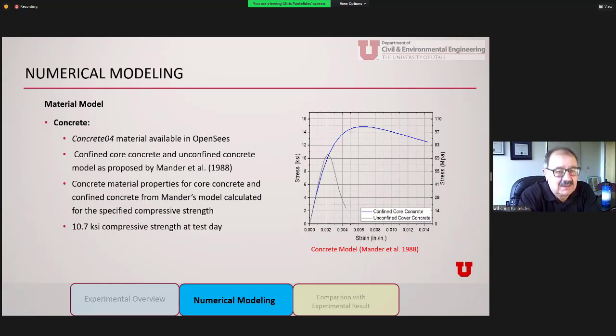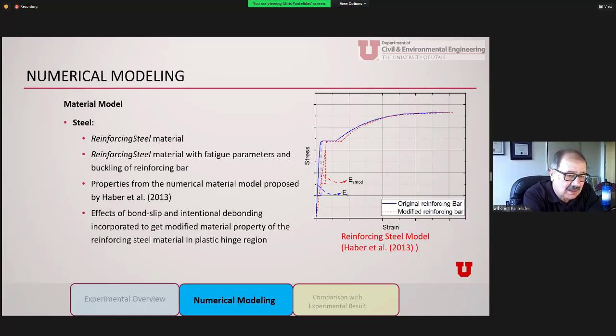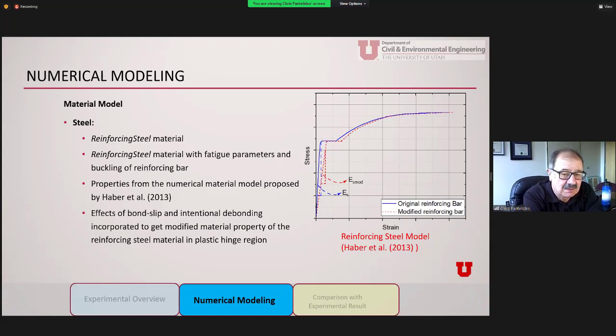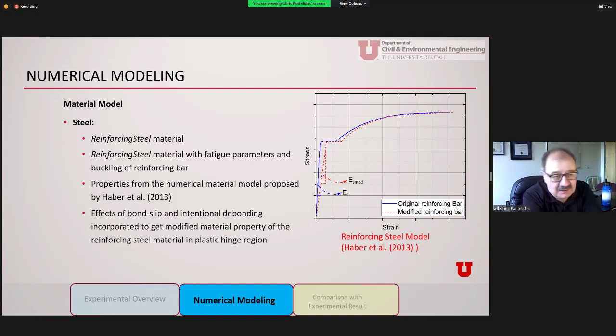The concrete compressive strength was rather high — 10.7 KSI — partly because we got donated concrete and partly because delaying testing increases strength. The real innovation in this model is how to model the reinforcing steel bars, a difficult exercise because we have two effects: in cast-in-place concrete columns the rebar eventually slips, giving a bond slip effect; and additionally in these two tests we intentionally debonded eight bar diameters of the steel bars to improve ductility capacity.